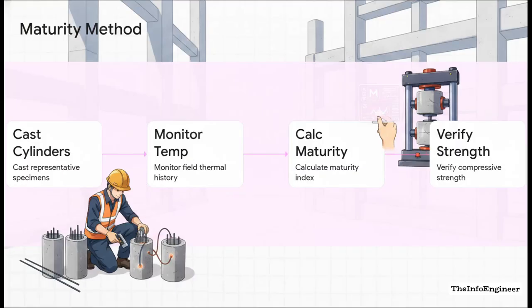And that right there is exactly why the absolute gold standard on modern construction sites is the maturity method paired with field-cured cylinder testing. Here's how it works. First, you don't just test cubes cured in a perfect, warm, cozy laboratory, you cast representative specimens and cure them under the exact same harsh site conditions as the actual structure. Second, you monitor the thermal history using embedded sensors. Third, you calculate the maturity index. And finally, you break those test cylinders at specific intervals. This rigorous progression is what actually verifies the real-time, in-situ field strength of your concrete.